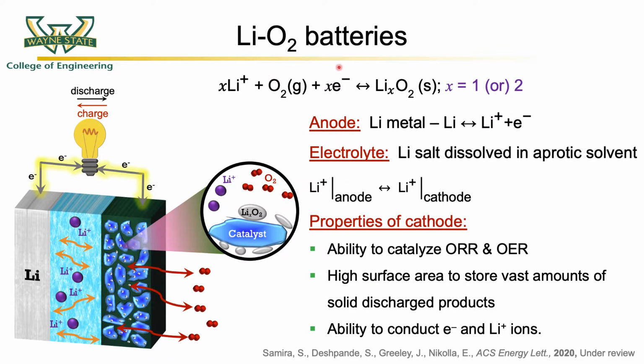These LiO2 batteries are a complex multi-component system consisting of a lithium metal anode, a non-aqueous aprotic electrolyte, and generally a carbon-based cathode. During discharge, the lithium metal is oxidized at the anode, leading to the formation of lithium ions, which are transported through the electrolyte, while the electrons are transported through the external circuit.